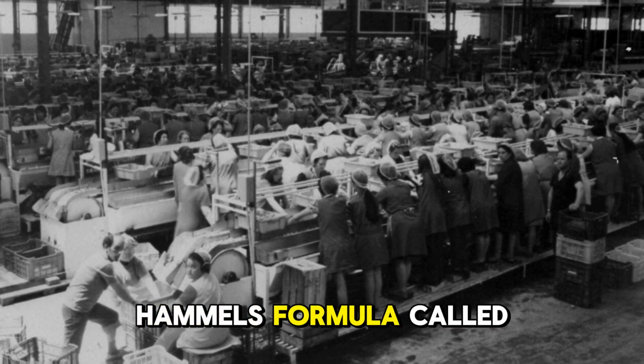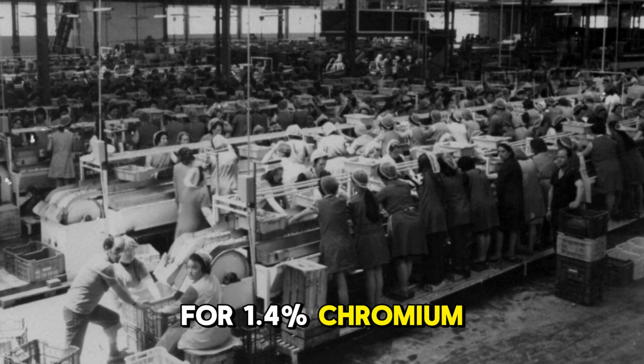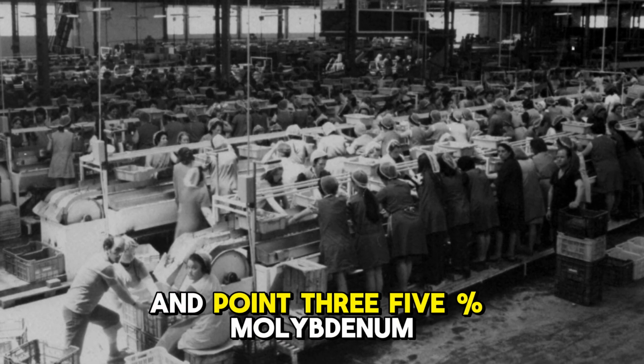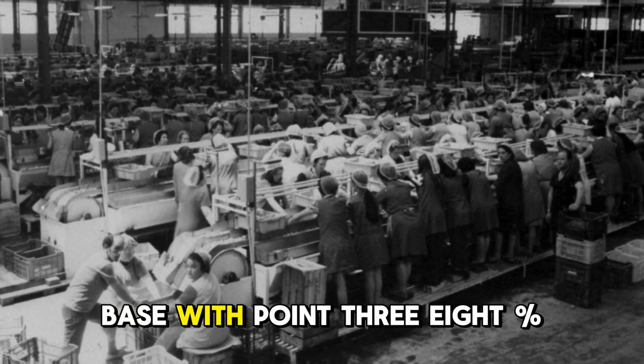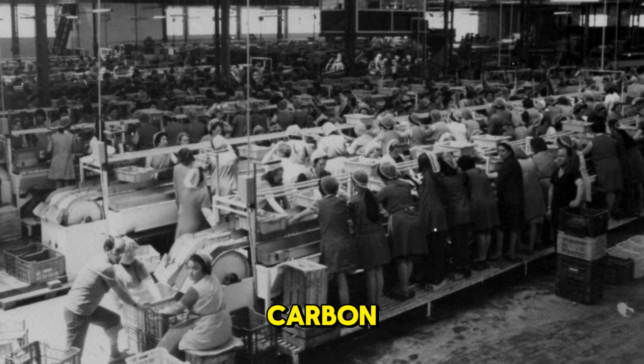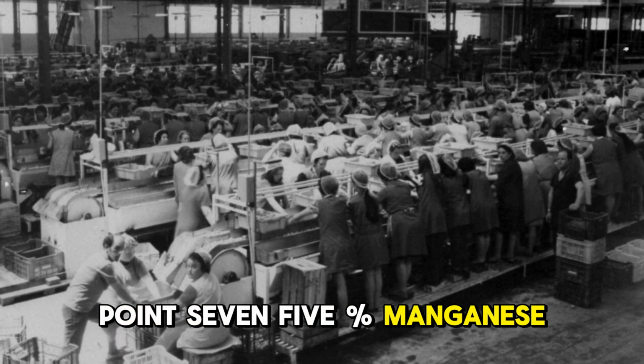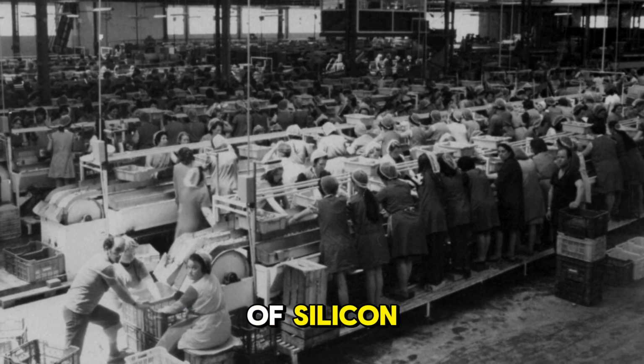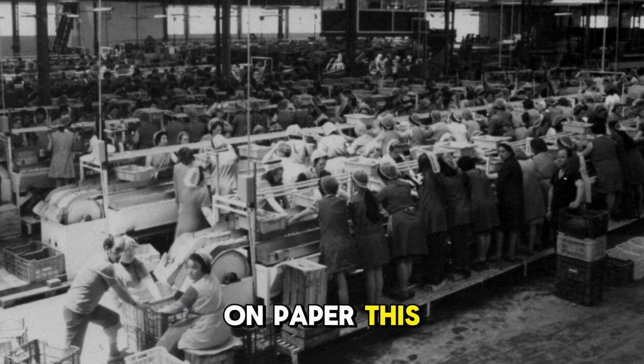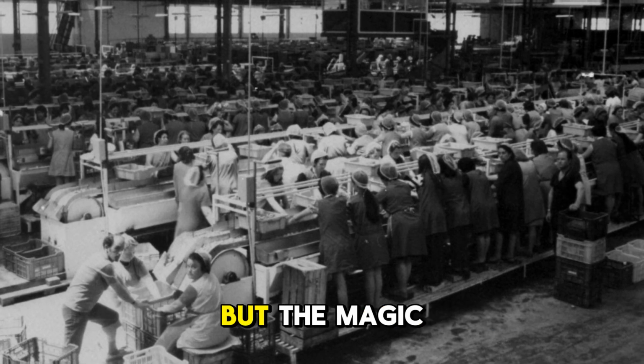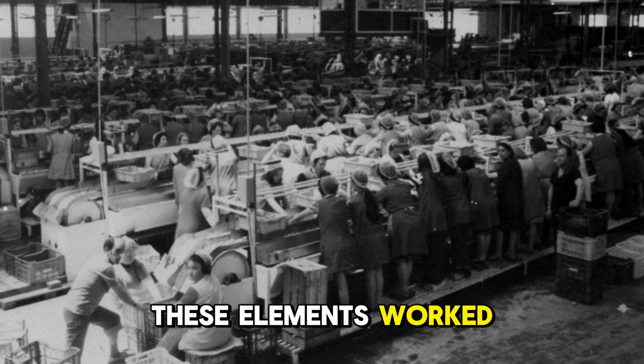Hammel's formula called for 1.4% chromium and 0.35% molybdenum in a steel base with 0.38% carbon, 0.75% manganese, and trace amounts of silicon. On paper, this doesn't sound revolutionary, but the magic was in how these elements worked together.